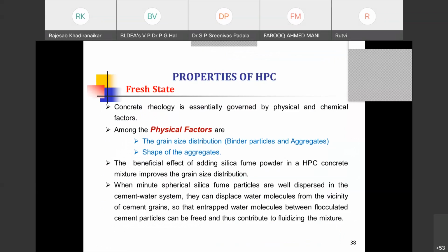Concrete rheology is another important property, how it behaves: stiffening, hardening, all those things. This is governed by physical as well as chemical factors. Among the physical factors, the grain size distribution of the binder particles and aggregates, and the shape of the aggregates also matter. The beneficial effect of adding silica fume powder in a high performance concrete mixture is that it improves the grain size distribution, that is the particle size distribution, what we normally call. So when minute spherical silica fume particles are well dispersed in the cement water system, they can displace water molecules from the vicinity of the cement grains so that entrapped water molecules between the flocculated cement particles can be freed and thus contribute to the fluidizing of the mixture.